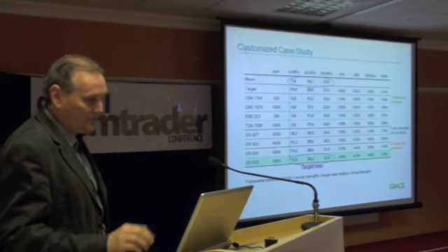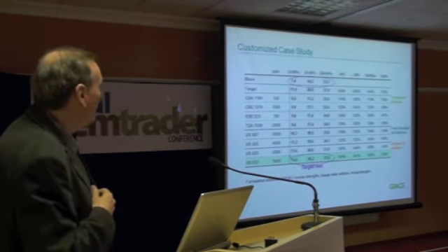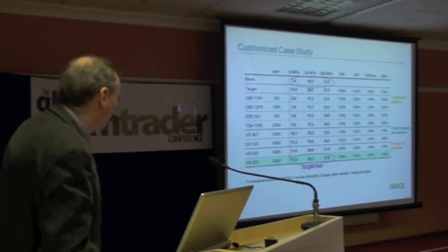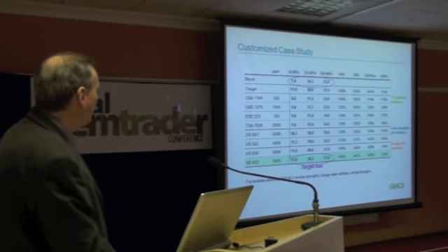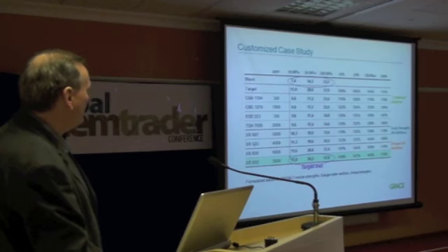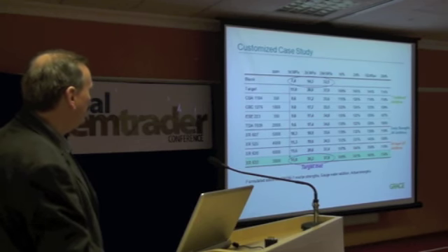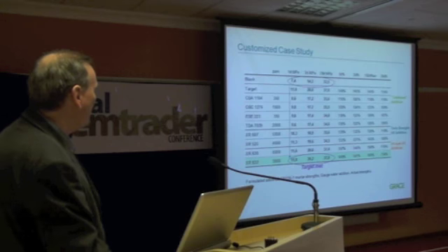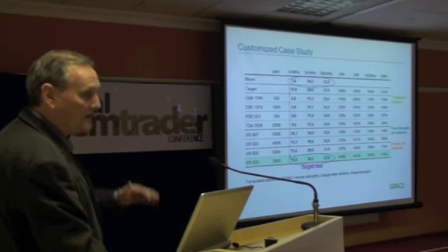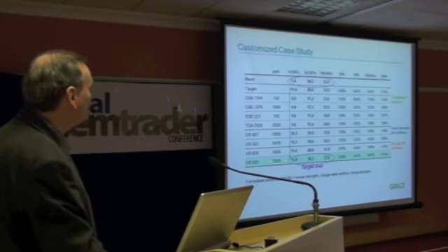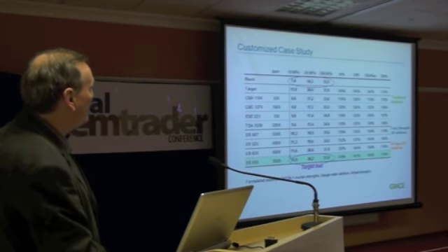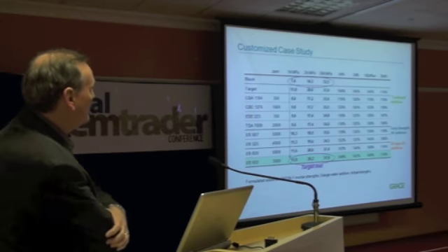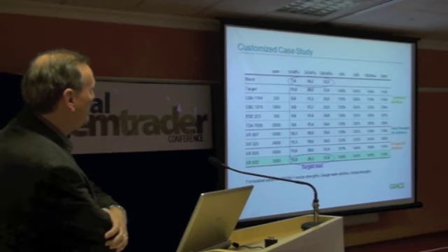And it's proving to some extent. So we don't apply it everywhere. But I'll just go through this example to finish off. This was a CEM 3, CEM 4, I think, very high, low clinker factors. So it was very high SCMs, and barely giving a 32.5. So the blank cement was giving 7 at 1 day and 32.5 at 28 days.